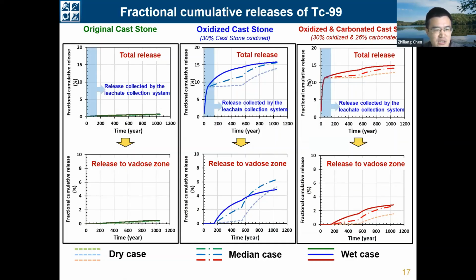So the results on the left are the release from the original cast stone, and the results in the middle are the release from the oxidized cast stone. And on the right are the results for the oxidized and carbonated cast stone. So the top 3 figures are the results of the total release, and the bottom 3 figures are the results of the release to the vadose zone. The release to the vadose zone is derived by subtracting the release of the first 150 years from the total release, because the release of the first 150 years is assumed to be completely collected by the leachate collection system sump at the bottom of the facility.